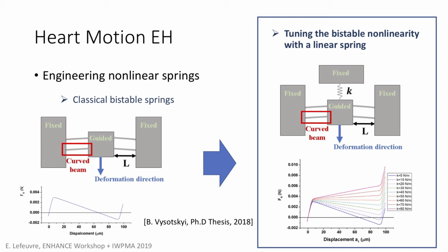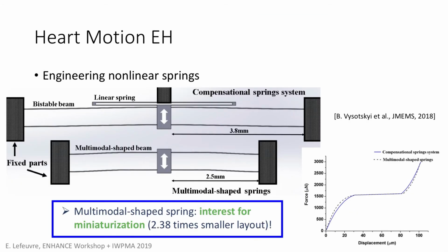So the idea here was to add a linear spring to change the slope of the total force-displacement characteristic of the system. So you have different slopes for different stiffness of this linear spring. So then once we had obtained the appropriate slope, we went to the practical design. So you have here the set of bistable beams and a linear spring on top of that. So with this design, we had what we wanted to have,